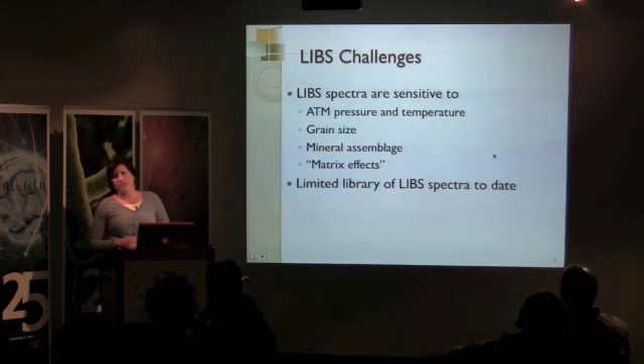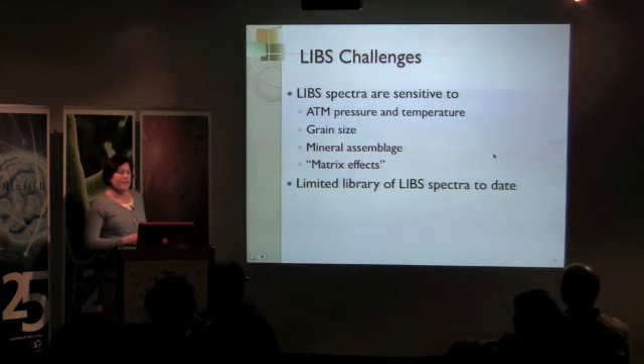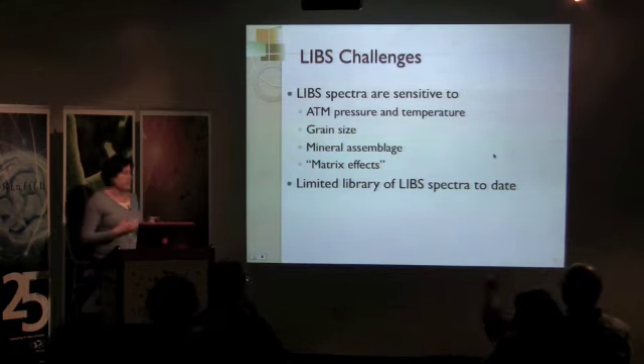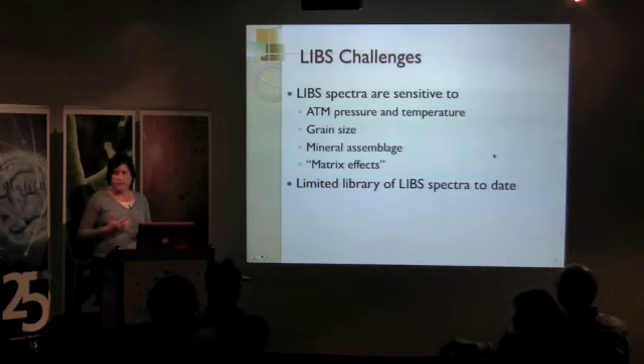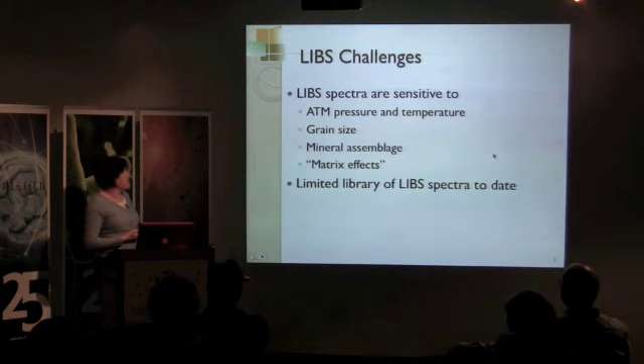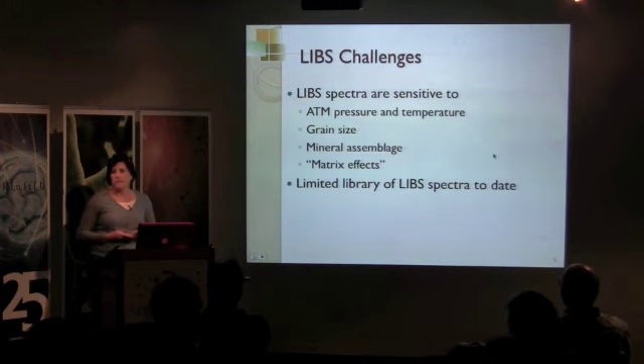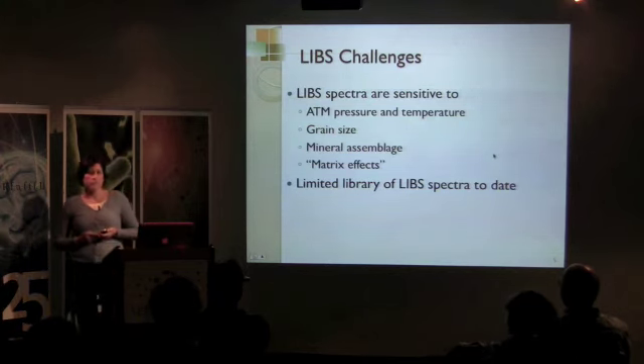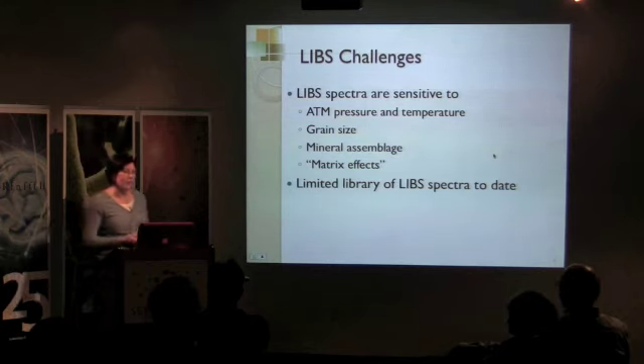Some of the challenges associated with LIBS are outlined here. LIBS spectra are sensitive to changes in atmosphere and temperature. So in other words, everything needs to be calibrated. Also sensitive to grain size. Because the LIBS laser spot is typically less than 1 millimeter, you have to really watch where you're pointing it or know where you're pointing it.